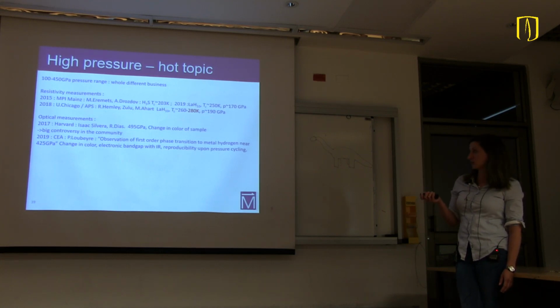The other big players in the field right now, at Harvard, Isaac Silvera and his, I guess, postdoc at the time, Dias, were looking at the metallization of hydrogen, not the alloys, but still hydrogen, and looking at the change of color in samples. When a sample goes from insulator to metallic, you're supposed to see a change in color and a change in conductivity. But that was a massive controversy in the field because hydrogen is extremely reactive, so you don't know what it's going to react with, your gasket or anything. They did see a massive change in color, but it was not clear whether it was pure hydrogen or reacted with something else.